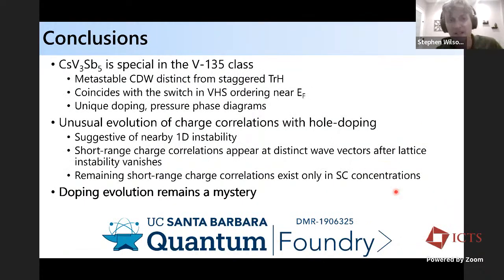But what I want to emphasize for this particular part of the talk is that the CsV3Sb5 system is special in the class of these materials in that it seems, in its pristine state, to form a metastable charge density wave phase, which is distinct from the simple staggered trihexagonal stacking. And this seems to coincide with a switch in the Van Hove singularities close to the Fermi level. It also has unique doping and pressure phase diagrams, which I didn't have a chance to talk about, which is also consistent with it undergoing a change in the charge density wave phase as you perturb the system. So the doping evolution remains a mystery, and our current model is suggestive of a nearby one-dimensional instability in the phase diagram.